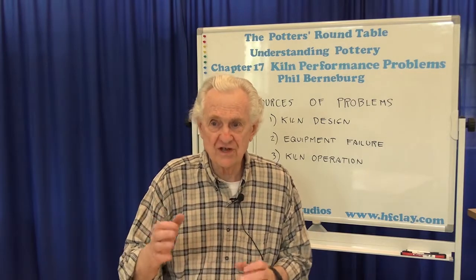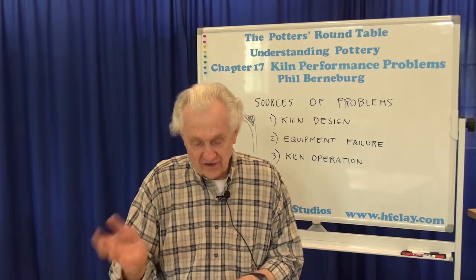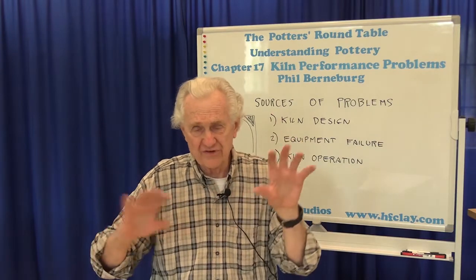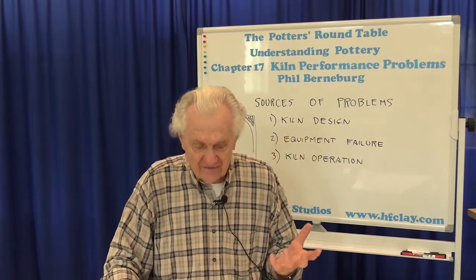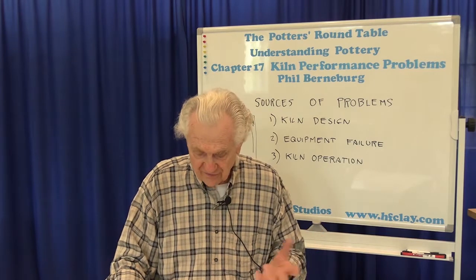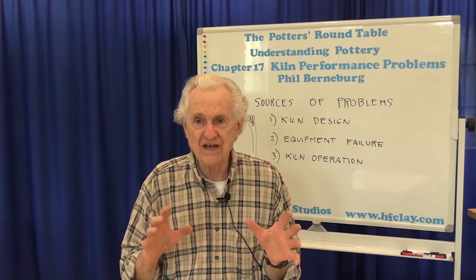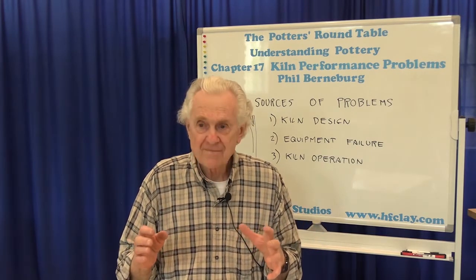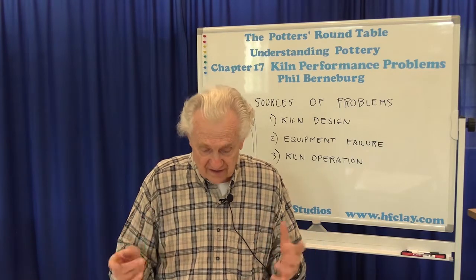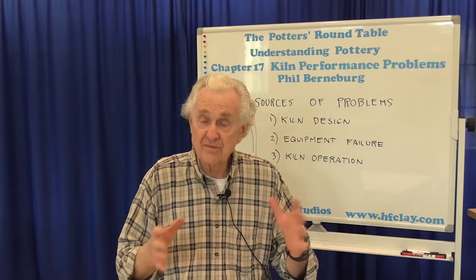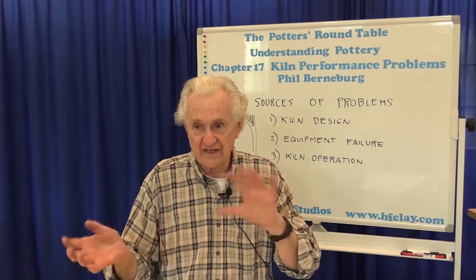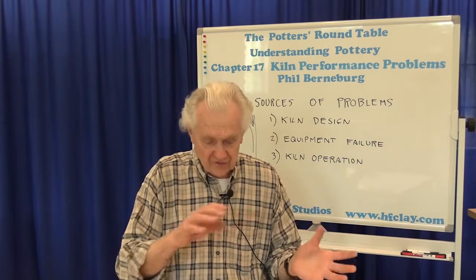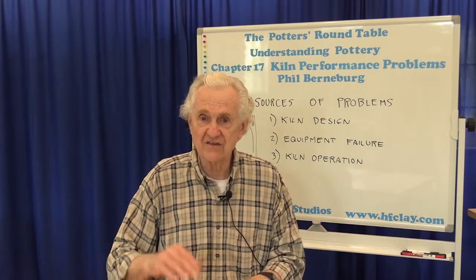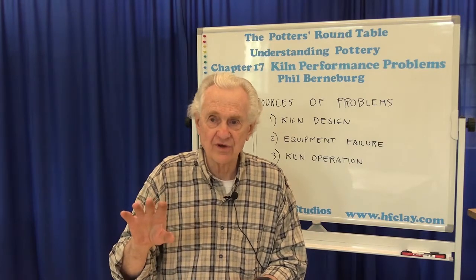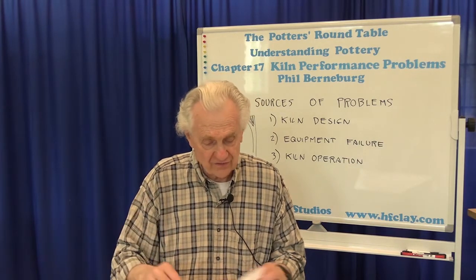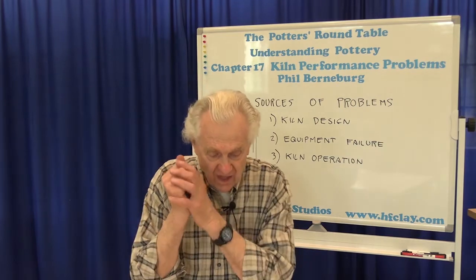Non-uniform reduction, not so much that I got it or not, but it doesn't seem to be uniformly positioned around the kiln. This goes back to the same idea about hot and cold spots. It could be that I'm getting poor mixing of the gas and the air. That could be the design of the kiln, and again, it goes back to stacking. The same conditions that can give me hot and cold spots can also contribute to non-uniform reduction. I can get spots where I'm not getting adequate flame to it, so I'm not getting good reduction conditions.